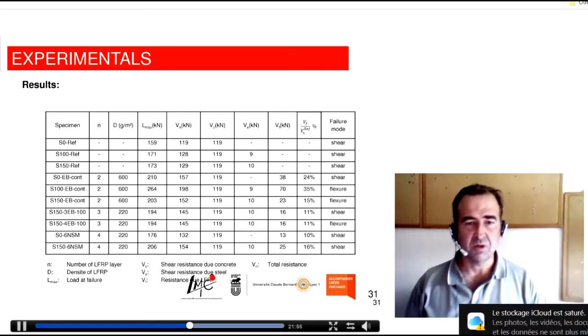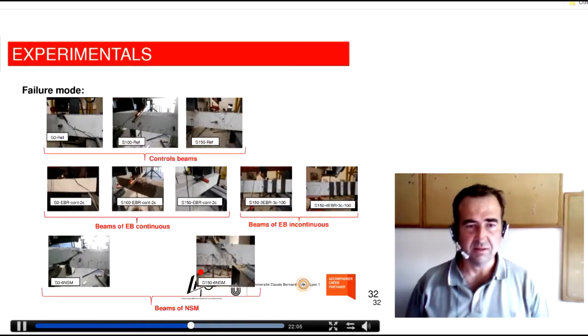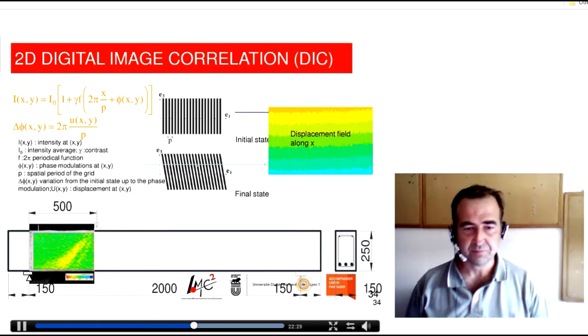And in some cases where the strengthening is very light, what we get is a very low level of increase of load, less than 10%. Some photos about the shear failure. You can observe here the cracking, specific shear cracking we have in different specimens. And one thing that is very nice to see is that we didn't get flax debonding, but we've been able to get the failure in tension of the flax fibers.